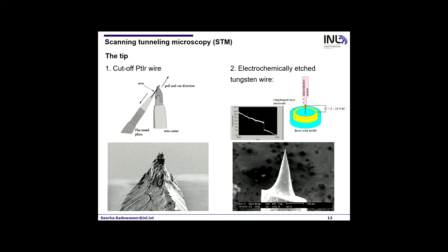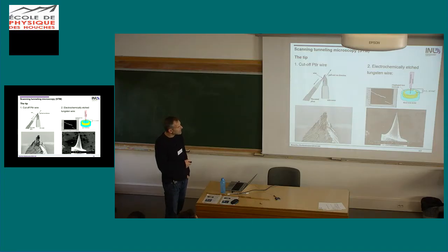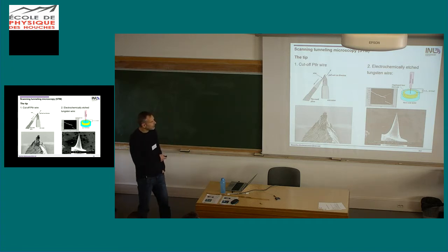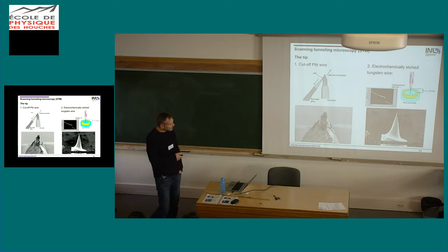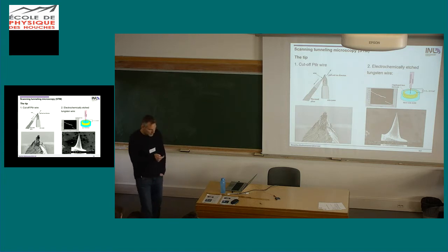So what's mostly done is actually electrochemical etching of a tungsten wire. So you have a KOH solution here, a ring electrode, and then you have a wire in a controlled way inside this ring. You apply a voltage between your wire and the ring electrode, and then you have electrochemical etching right at the surface of the liquid. And this etches your tip until you get the meniscus where it just drops off. So this is the current as a function of time, and at some point just the bottom part of the wire drops off, and then you pull out and you remain with a very sharp tip. And this one you can still prepare a little bit further inside the ultra-high vacuum system to get it even better.